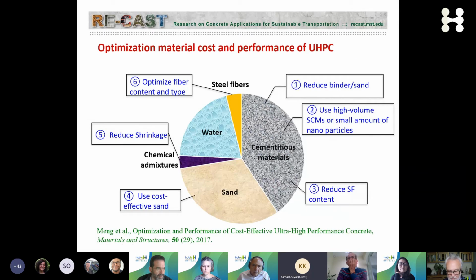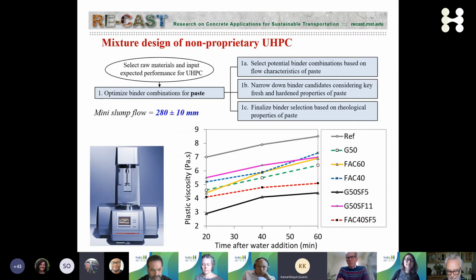And at Missouri S&T, through the RE-CAST University Transportation Center, we've been working with our partners to try to reduce the unit cost of this UHPC by making different innovations, whether it is on the selection of the binder materials, or the fibers, or the sands, trying to reduce shrinkage and cracking of such concrete. And our designs quite a bit are driven also by rheology. These concretes are extremely fluid, but also extremely viscous, making it much more difficult and time-consuming to cast them.